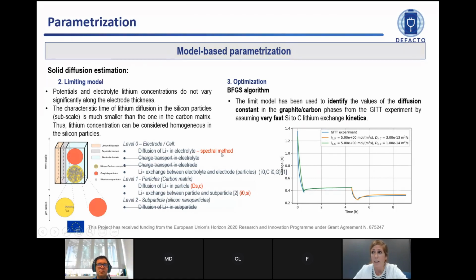So for these limiting models, we account for the diffusion of lithium in the electrolyte, but this is approximated by the spectral method just to make it run more efficiently. Then in level 1, we have carbon and graphite that is not taken into account, but we have considered it here. And here, we are taking into account the diffusion of lithium in the particle, and even the exchange between the carbon matrix and the silicon. What we are eliminating in the limiting model is the diffusion of lithium along the silicon. So here again, we apply a quasi-Newton approach to minimize the error, or to identify the objective function, and to obtain the value of the diffusion